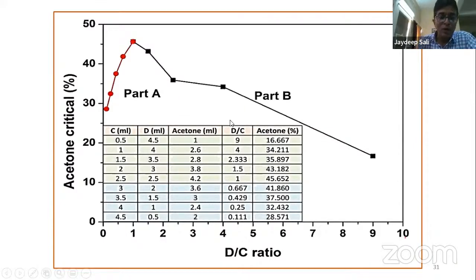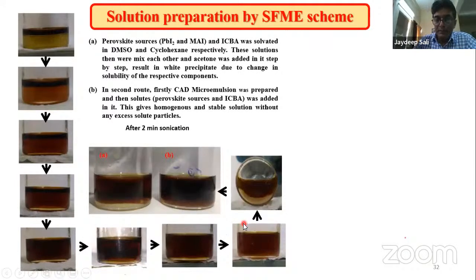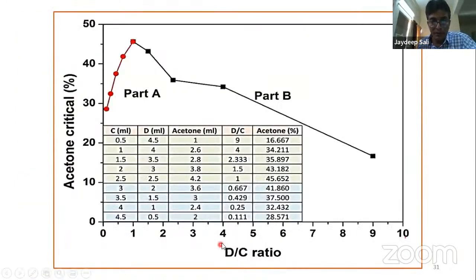of perovskite. Now we have observed that this is the ratio of DMSO. The x-axis indicates the ratio of DMSO and cyclohexane. Okay, so if the ratio of DMSO and cyclohexane, that is the two solvents which are forming the microemulsion, is changed, then we need a different proportion of acetone to stabilize the microemulsion. For example, if the proportion of DMSO and cyclohexane is 1, that is they are in equal volume, then we need about 45% of acetone to stabilize the microemulsion. Meaning if the acetone is less than 45%, the microemulsion will be unstable and both these solvents will totally separate away from each other. And if the acetone volume is greater than 45%, then and only then the two solvents will form a microemulsion state.